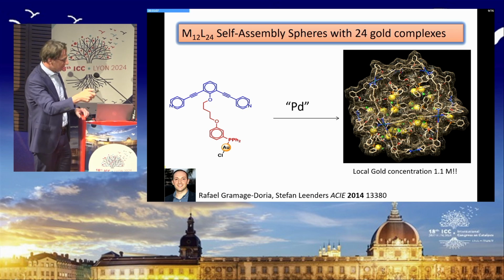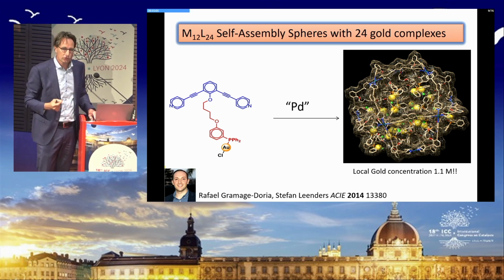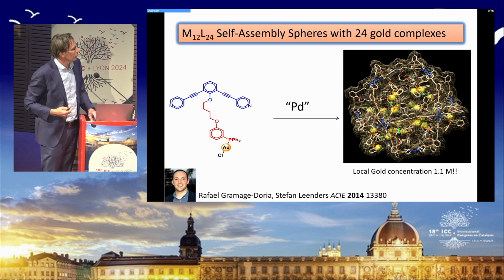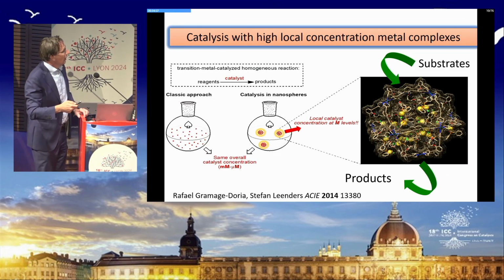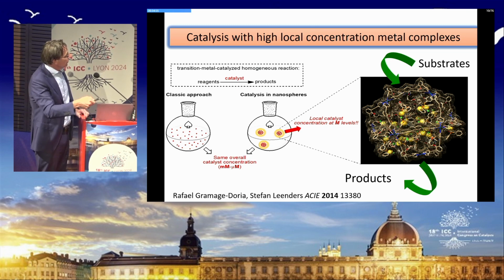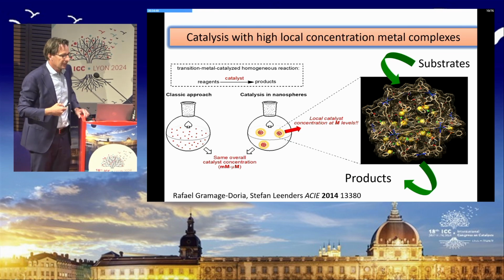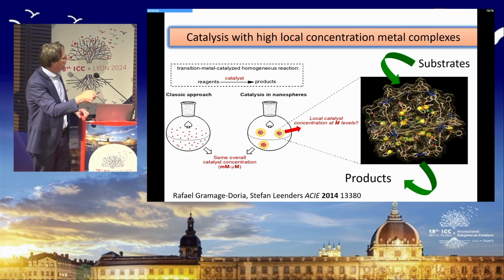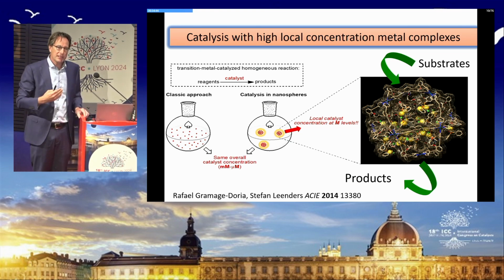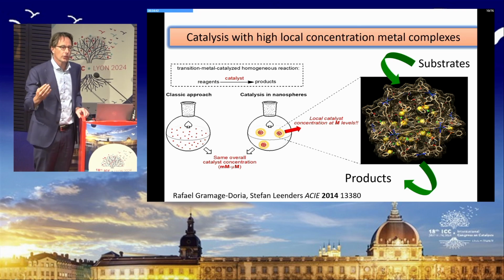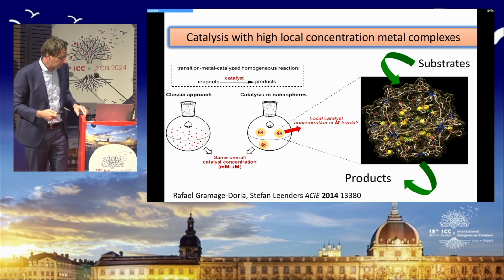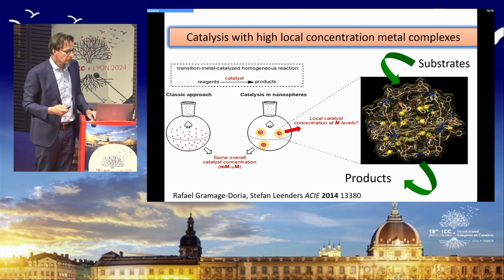So from that you can estimate that this is really a high local concentration of gold. Basically an unexplored area in catalysis, extremely high local concentrations. So what we do, we make these nanocages with high local concentrations of gold, but the overall concentration in the flask is just typically millimolar to micromolar. So this means that we can still have high turnover number with respect to the substrate that we generate.